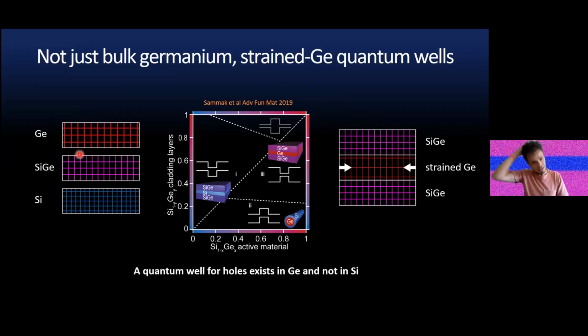Now, this is a challenge and an opportunity, because from a material perspective, it's really a challenge to make heterostructures with very low disorder, because managing strain in these structures is very tricky, as they tend to introduce dislocations. On the other hand, this is a great opportunity to tailor the band structure. So here you see a bit of the playground that you can have with putting a layer of silicon germanium strained on top of a relaxed substrate, which we call a virtual substrate.